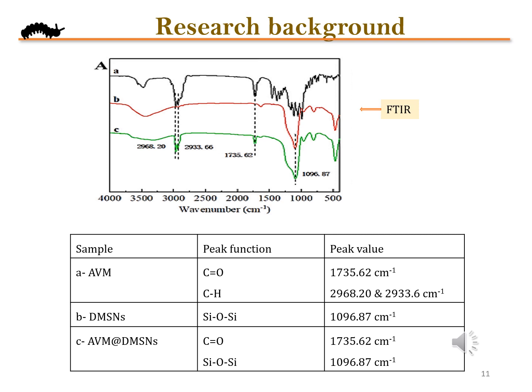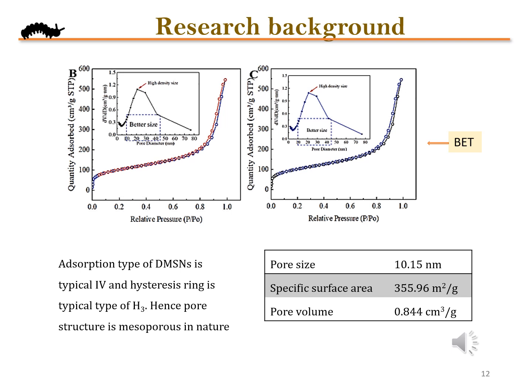1096.87 cm inverse. The BET analysis was performed to know the surface area of the material, and from the nitrogen adsorption analysis, the DMSNs show a typical type 4 graph, which shows that the synthesized material is mesoporous in nature. And from the analysis, the specific surface area was calculated to be 355.96 meter square per gram with a pore size of 10.15 nanometer and pore volume of 0.844 cm³ per gram.